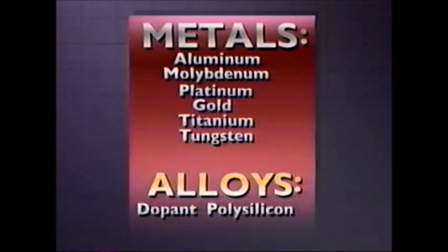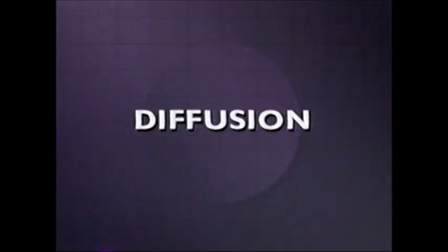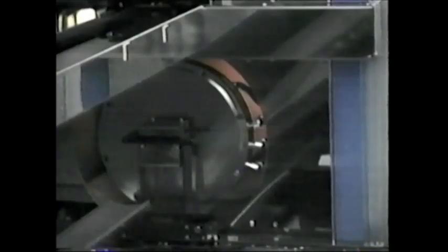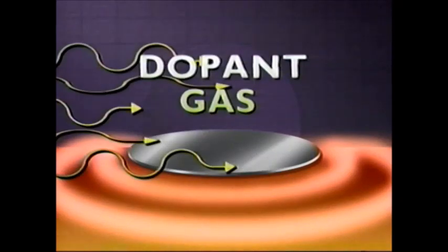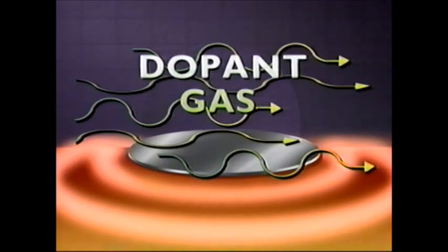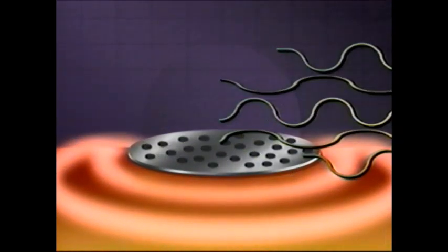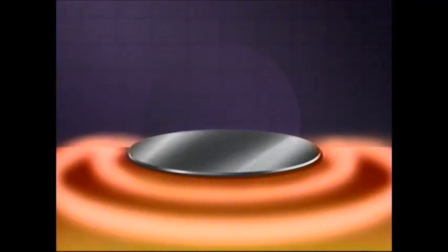Metals like aluminum, molybdenum, platinum, gold, titanium, and tungsten, and alloys like doped polysilicon are commonly used for the chip interconnects and bond pads. The diffusion process takes place in a quartz-lined furnace similar to an oxidation furnace. Dopant gas, which changes wafer characteristics, is forced to flow over the wafers. During this process, atoms of the desired impurities settle on the wafers. When the dopant gas is turned off, the impurities are given time to diffuse into the wafers.